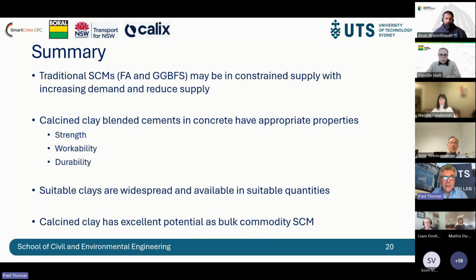And that basically brings me to an end. One of the aims of this was to test the feasibility, as there is a belief that traditional SCMs will face constrained supply with increasing demand, or reduced supply because of the closure of power stations. Calcined clay shows a lot of promise because you can get suitable strength, suitable workability, and produce durable materials. Calcined clays are widespread, so there's no problem with niche material - we're not talking about a sprinkling of clays or small volumes available. So it has excellent potential as a bulk commodity SCM.